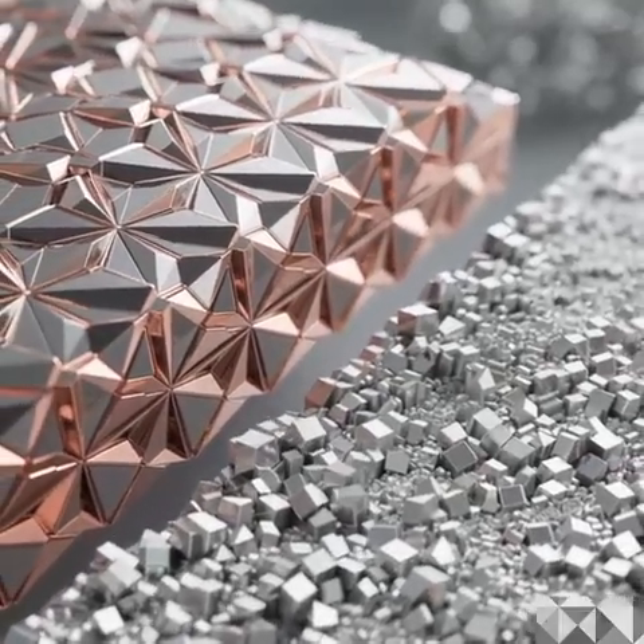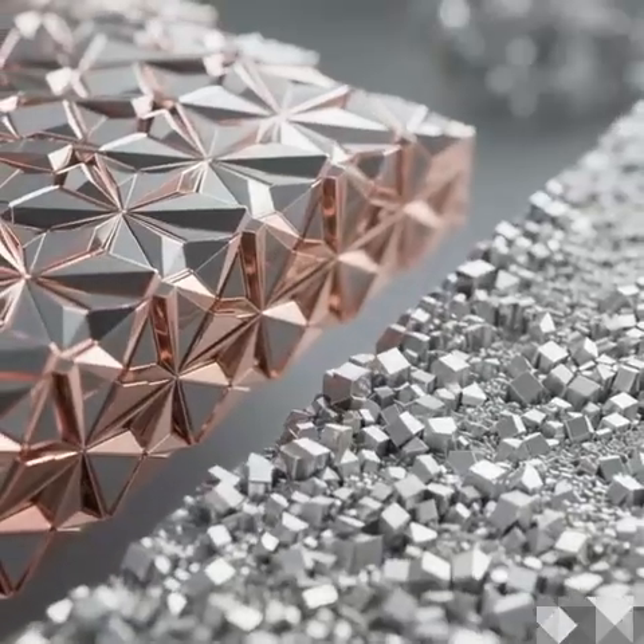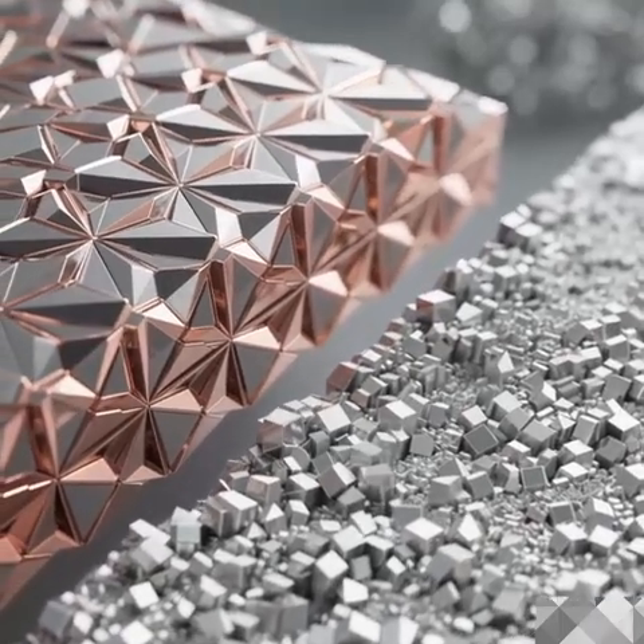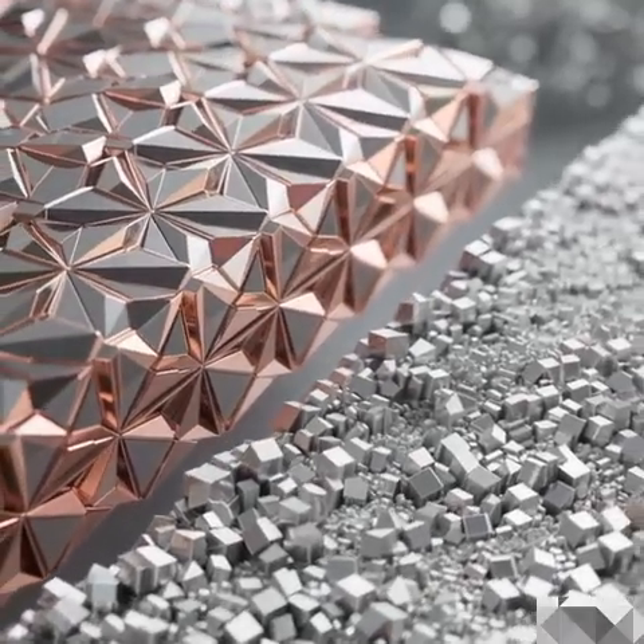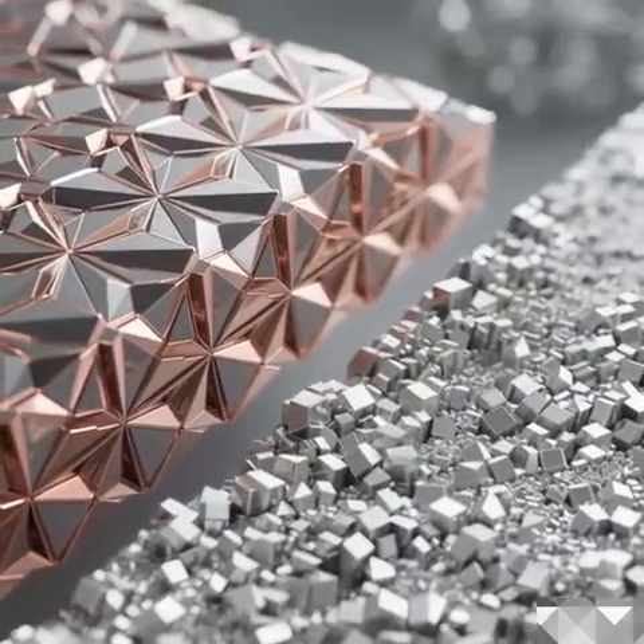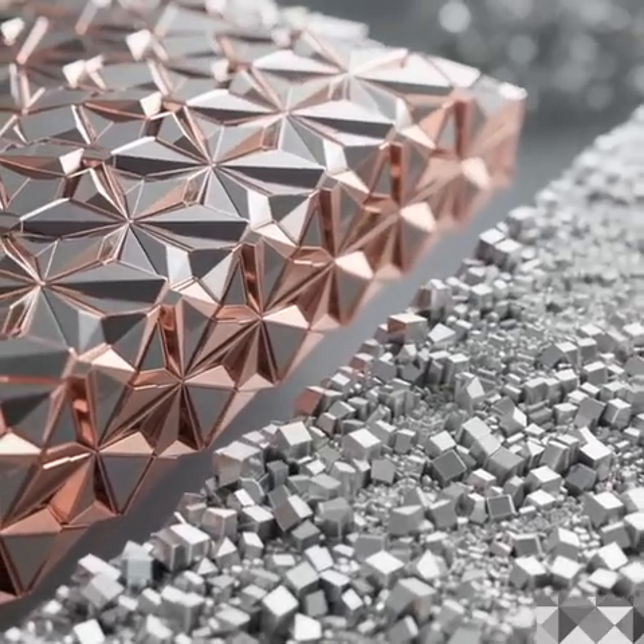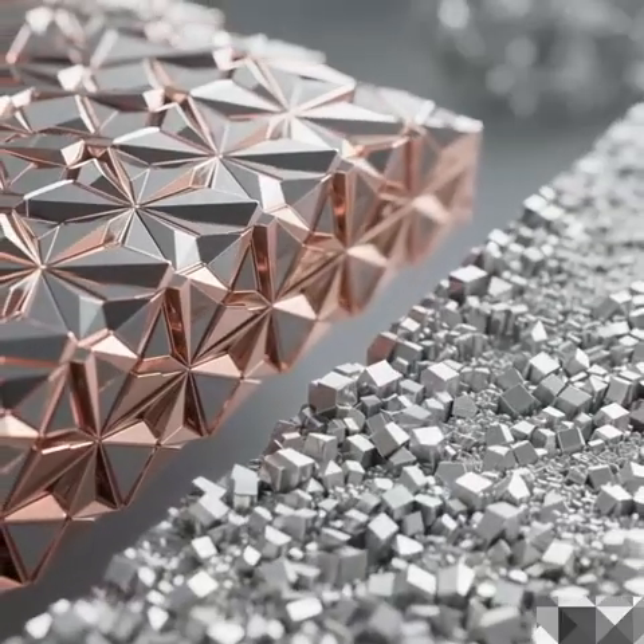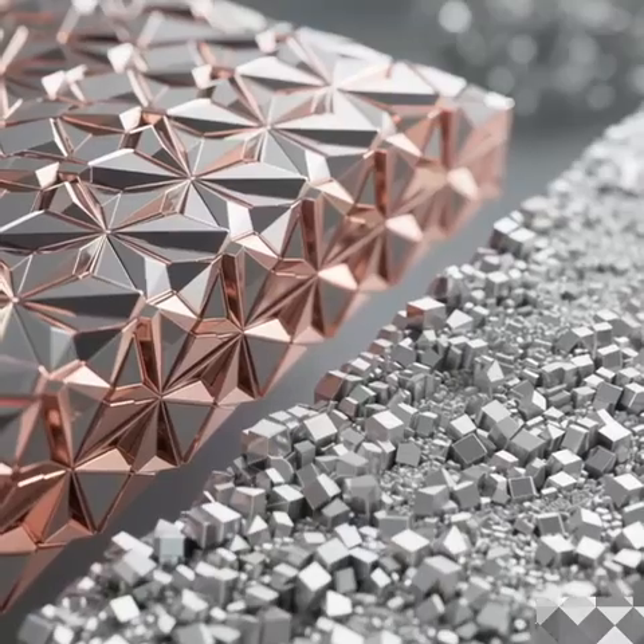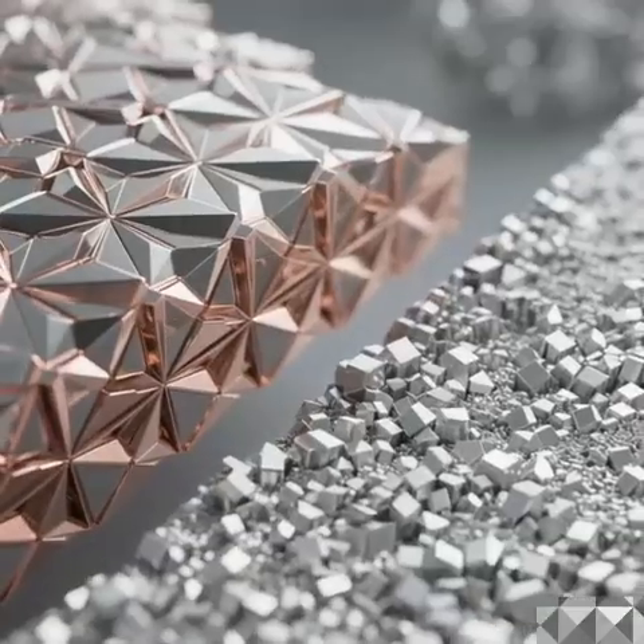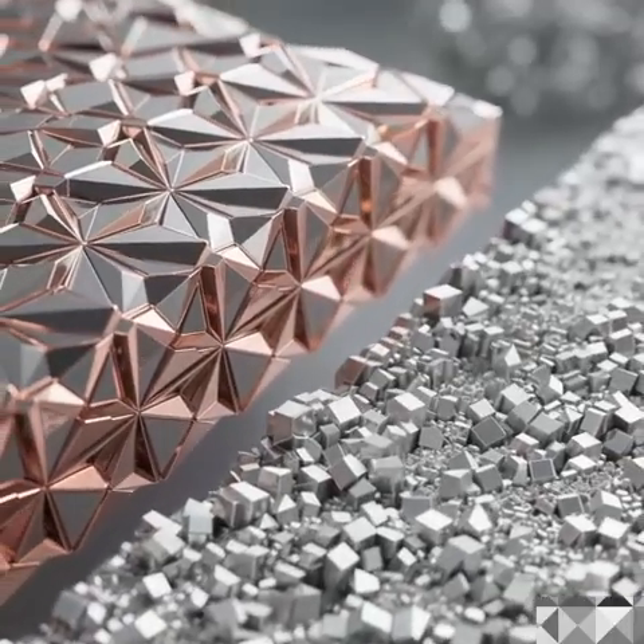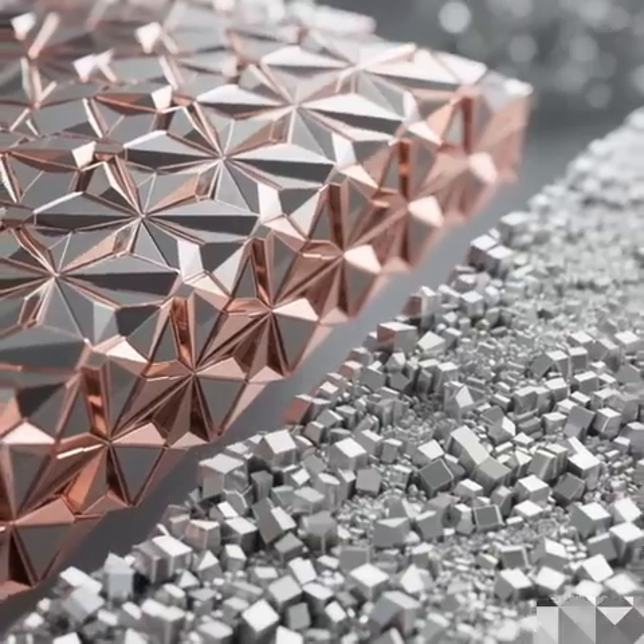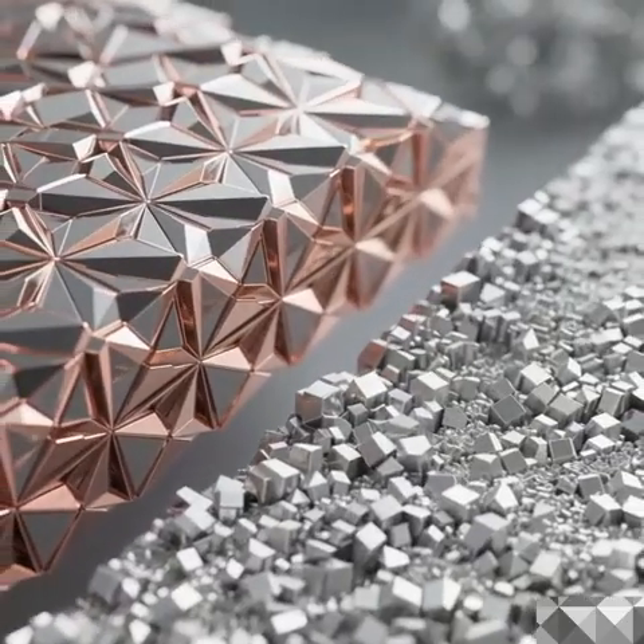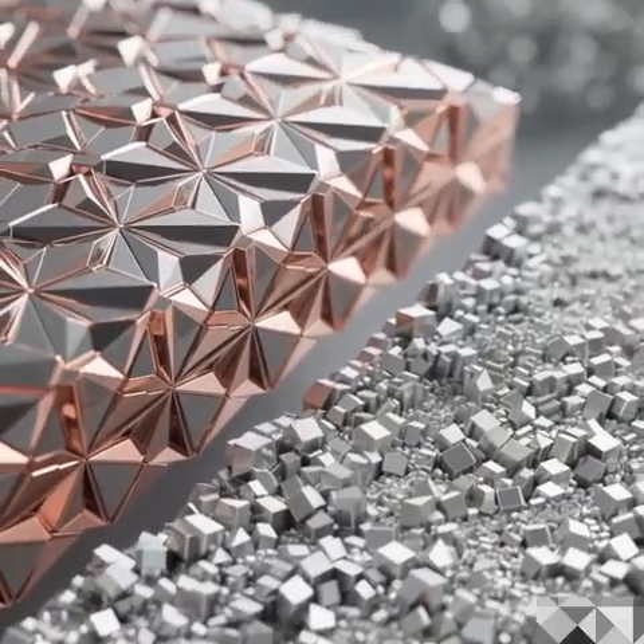They move via something called creep-assisted diffusion. It's like they're actively guided to fill in any tiny gaps or voids at the interface. So it kind of self-repairs the connection as it forms. In a way, yes. It leads to this incredibly dense, almost pore-free bond, and it happens fast, maybe 10 minutes. Just 10 minutes. At what temperature? Even down between 150 and maybe 200 degrees Celsius, way below typical bonding temps.